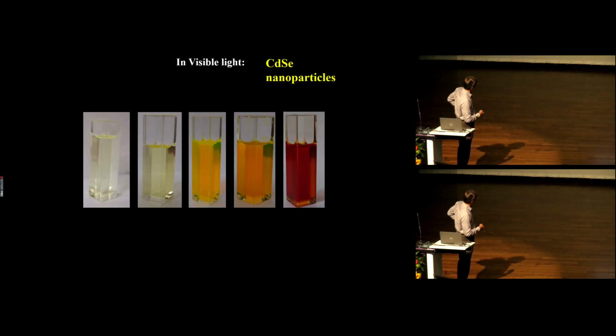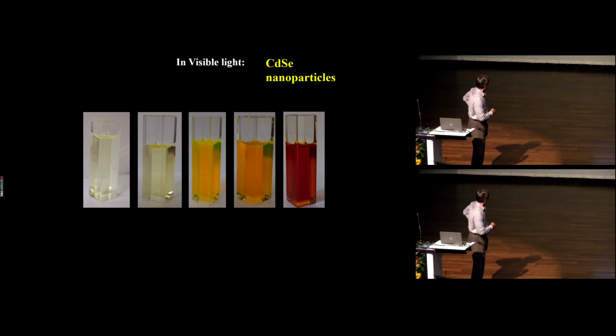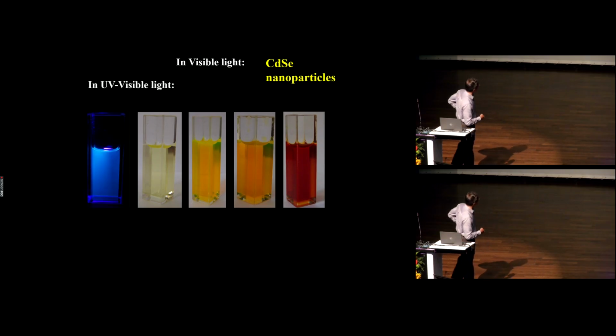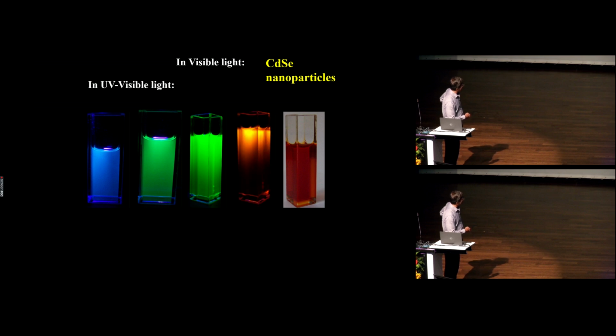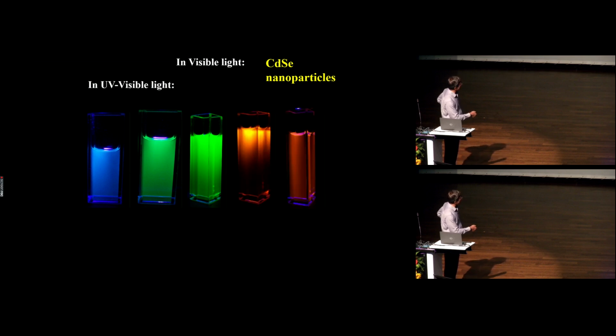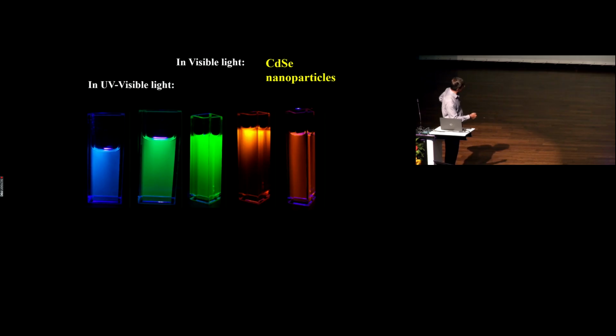Here's an illustration. All these are different size cadmium selenide nanoparticles. The color that you're seeing is actually scattering color, not the real color of the material. What we are going to do is shine UV light on it, and you can see that cadmium selenide, though the material remains the same, changes the color that comes out of it drastically, spanning the entire range of visible color. Therefore, you have control of all possible colors.